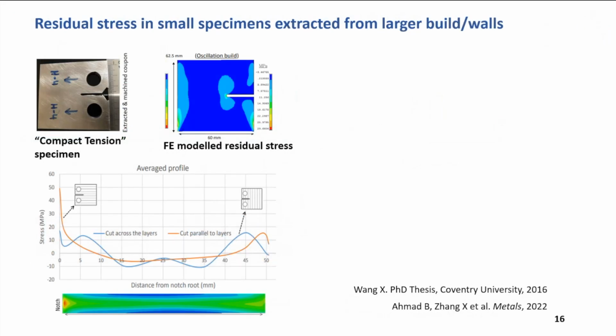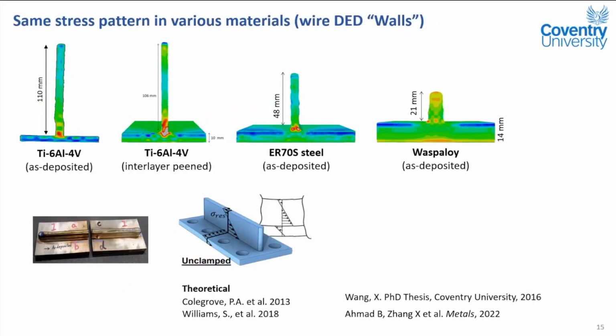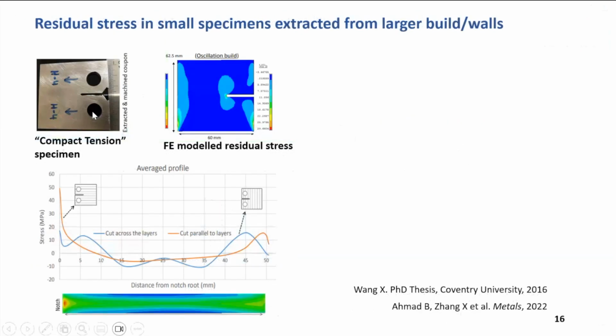So this slide is quite important. What I really want to say is in the wall, residual stress is quite high. It's about the yield strength of the material. But when you actually extract these very small compact tension samples or tiny small dog bones for tension, all of them are released because there are free boundaries. There's no material to hold the residual stress, so they are released.